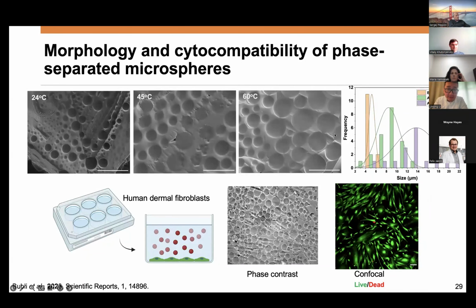We did the SEM morphology show. Then during the phase separation, they form these sort of defined microparticles, and then as you increase the temperature, you also have the larger particles. We also test out the cytocompatibility of the particle. Essentially, we incorporate the concentration 10 mg per ml of the dextran solution in the culture media, which can phase separate at 37 degrees.